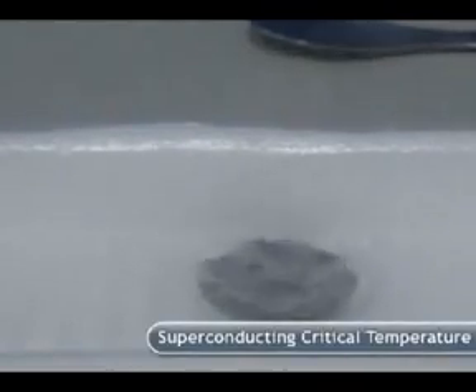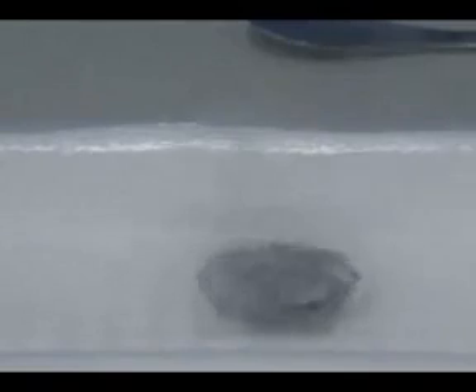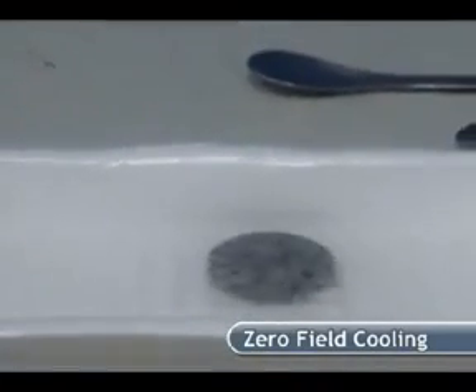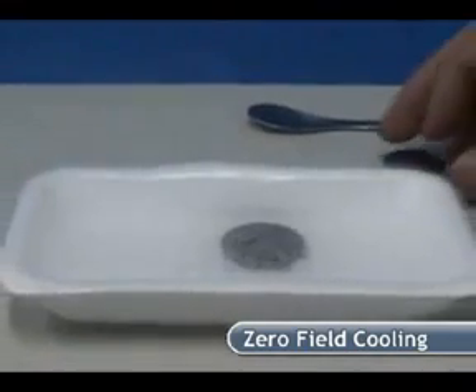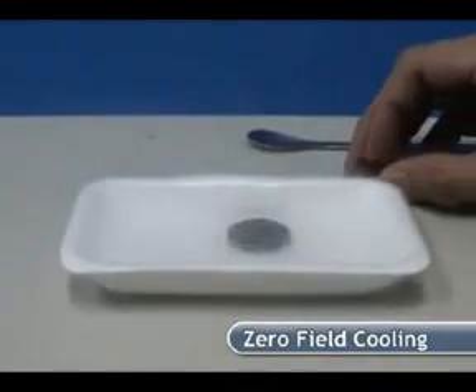This indicates that the temperature has cooled below the superconducting critical temperature, or 91 degrees Kelvin for the yttrium barium copper oxide compound, and it has established superconducting properties. In the process of cooling, the superconductor was not placed near a magnet. We call this cooling condition zero-field cooling, which means the superconductor is cooled with no outside magnetic field influence.